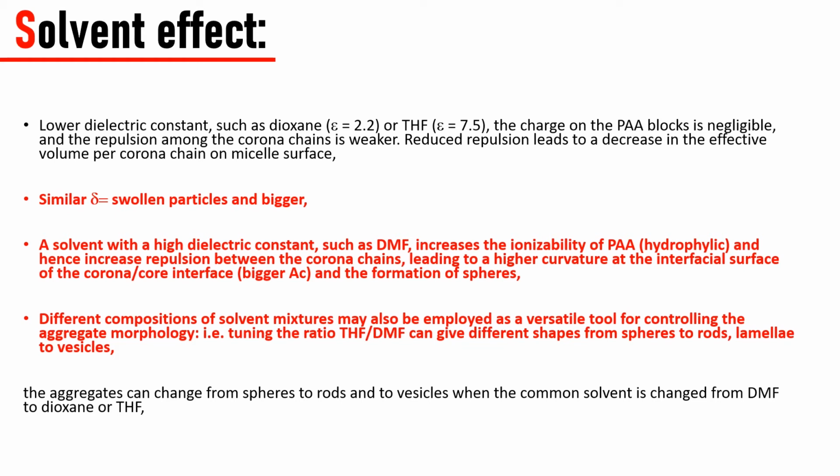However, for a solvent with lower dielectric constant, such as dioxane or THF, the charge on the polyacrylic acid blocks is negligible, and the repulsion among the corona chains is weaker. Reduced repulsion leads to a decrease in the effective volume per corona chain on the micelle surface. In summary, if the chain and the solvent have similar solubility parameters, the particle is swollen with an increased core size.